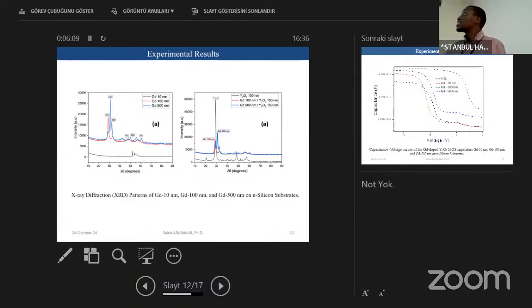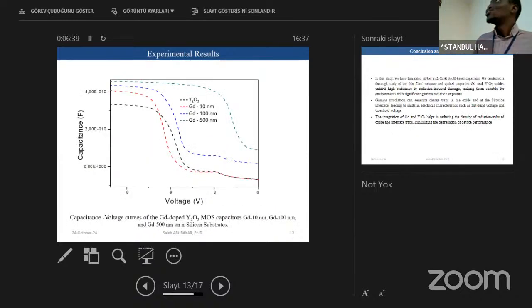Because you can see here, the single yttrium oxide has high intensity, but when you deposit the gadolinium oxide, here we are not working on the crystallinity or structure of the material. We just want to see how gadolinium would affect the gate oxide material. So you can see there is an angle shift and also a decrease in the intensity of the material, because gadolinium oxide is a metallic material, right? So that's why we are working on it here.